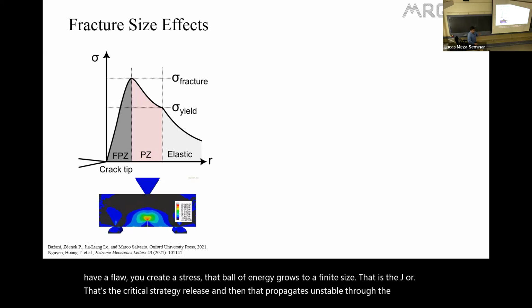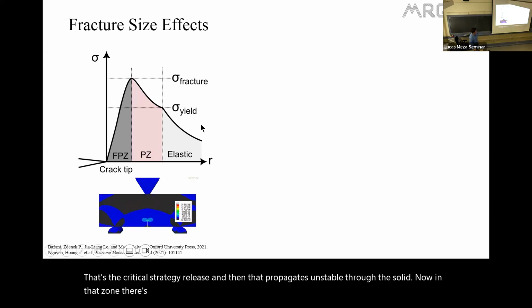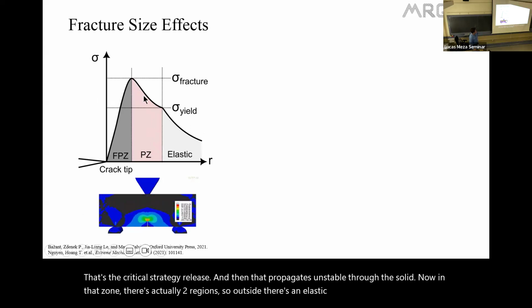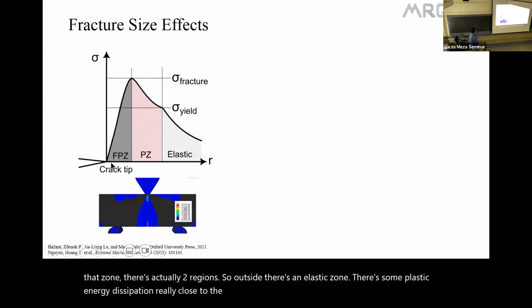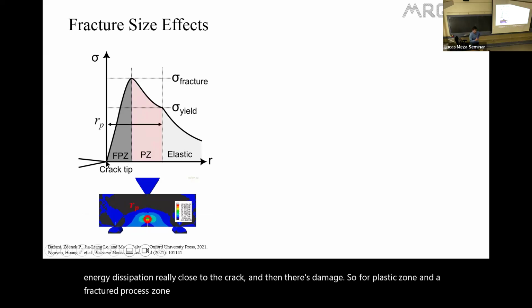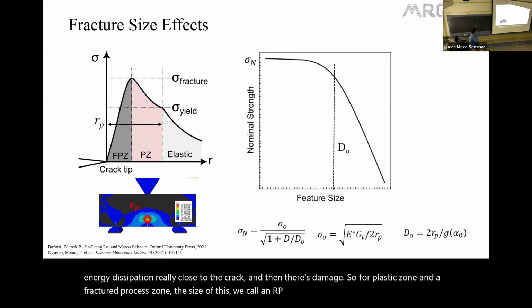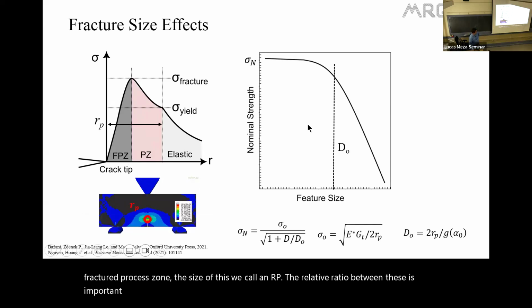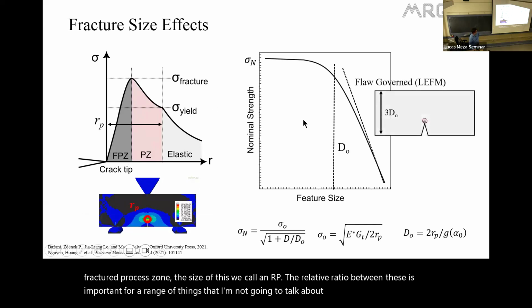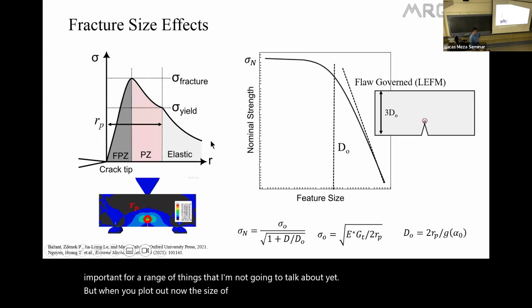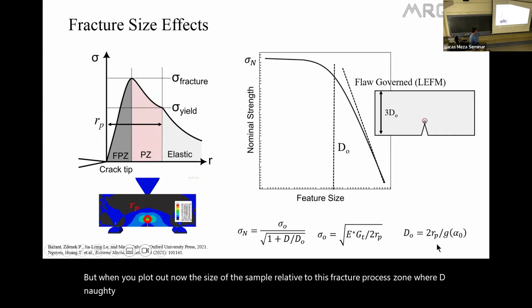solid. Now, in that zone, there's actually 2 regions. So outside, there's an elastic zone, there's some plastic energy dissipation really close to the crack, and then there's damage. So a plastic zone and a fracture process zone. The size of this, we call an RP. The relative ratio between these is important for a range of things that I'm not going to talk about yet. But when you plot out now the size of the sample relative to this fracture process zone, where D naught is a non-dimensional figure of merit, D is a length figure of merit related to the RP with some geometric corrections in there.